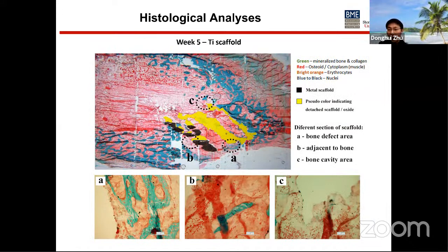Here is the titanium control. Similarly, vascularization is observed both inside and around the scaffold. Also, some mineralized bone on the surface is observed in the defect region.